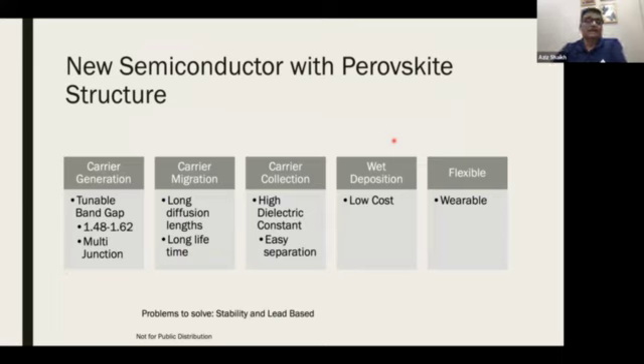Okay. Then finally, there has been a lot of excitement on the new semiconductor, which is called perovskite. From the carrier generation point of view, they have a tunable band gap. So band gap is from 1.48 to 1.62 eV, and you can change this band gap even further. So you can use it in multi-junction cells. The carrier lifetime is very good, so long diffusion lengths, long carrier lifetime. So migration wise, it is helpful. Carrier collection is good because these materials have a higher dielectric constant than silicon. The higher the dielectric constant, there is a formula, you can get a better carrier separation. The costs are low because you can make these perovskites using wet deposition techniques, and you can form structures which are flexible, so you can wear them.